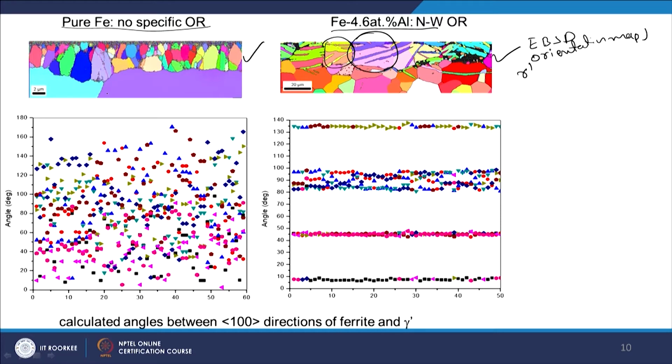This you do not see here, you have one grain and in that actually all possible colors of iron nitride are shown. That means it is not bothered about what the orientation of the BCC iron grain is, it is picking up its orientation randomly, whereas here it is picking with some relationship with the matrix, that is the BCC iron. So, that is what one can see with this kind of analysis. I will not go into the details.